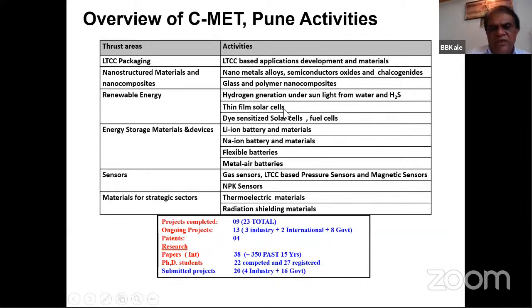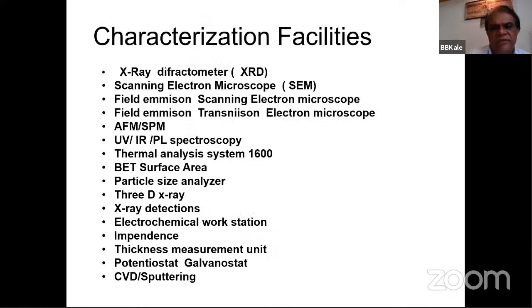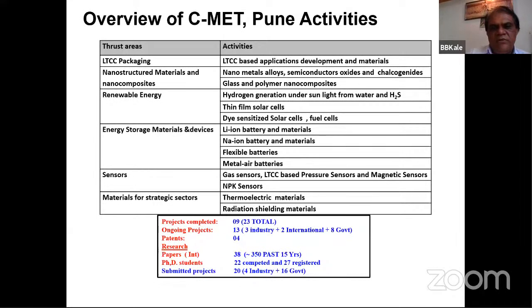Then a good facility of thin film solar cells. And this is also silicon. We also have tin oxide based solar cells. Then dye-sensitized solar cells, we have full facility. Now our scientists are working on cadmium sulfide based or zinc oxide based solar cells, and fuel cell technology. We developed a nano catalyst like platinum, and we tried to replace platinum with some other thing like a combination of other metals. And we found there is a combination where we get an equivalent amount of efficiency of the fuel cell catalyst.